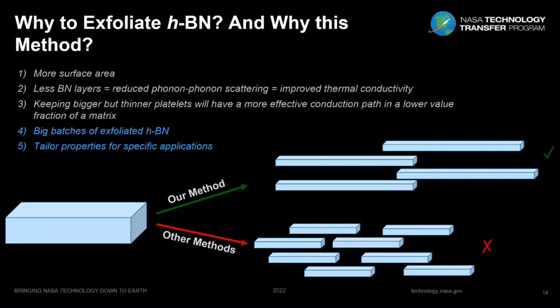For this, we need this technique. It can create more surface area. It can create fewer boron nitride layers that reduce the phonon-to-phonon scattering, and that will eventually improve the thermal conductivity. Keeping bigger but thinner platelets will help us have a more effective conduction path at a lower volume fraction of a matrix, and that's really important.